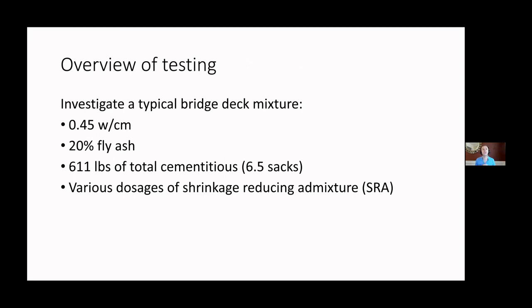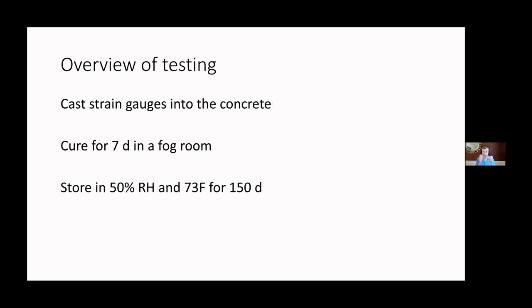We're going to start out testing some typical concrete that would be used for a bridge deck in Oklahoma: a 0.45 water to cement ratio, 20% fly ash, about a 6.5 sack mix, and we're going to be using various dosages of shrinkage-reducing admixture. We're going to actually cast strain gauges inside of our concrete, and we're going to cure them for 7 days to simulate curing that would happen on a bridge deck. And then we're going to store it at 50% relative humidity and 73 degrees Fahrenheit, and see how that strain changes over time.